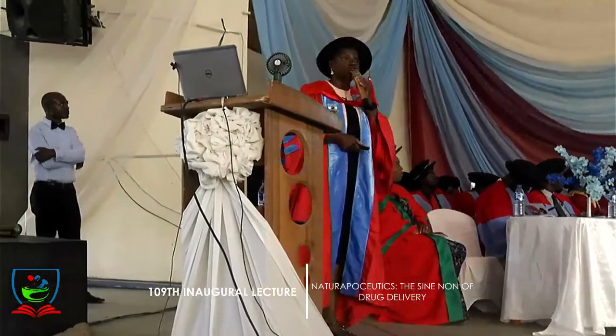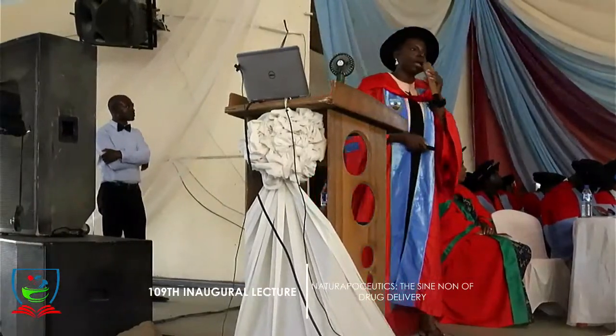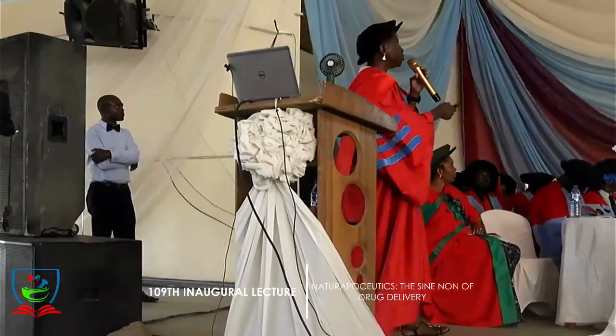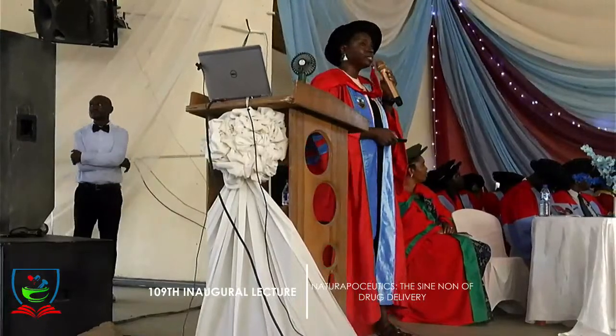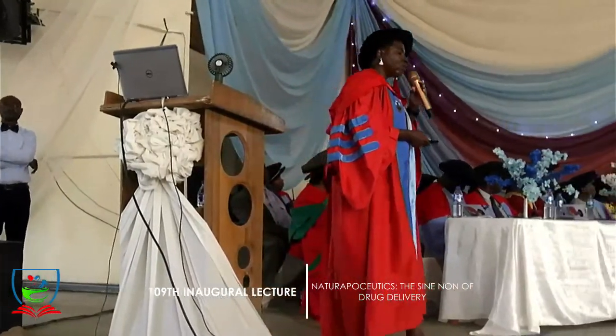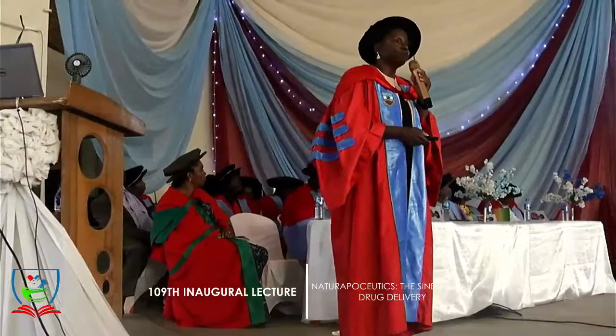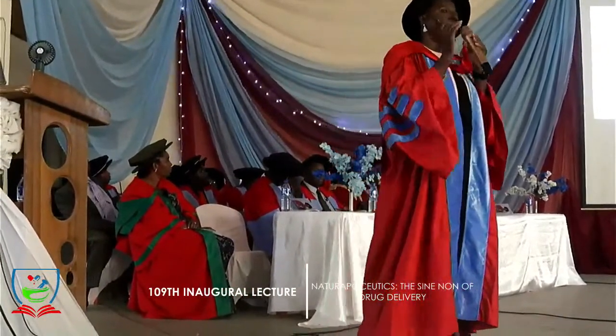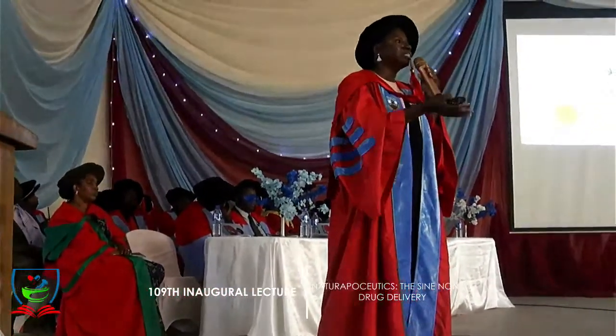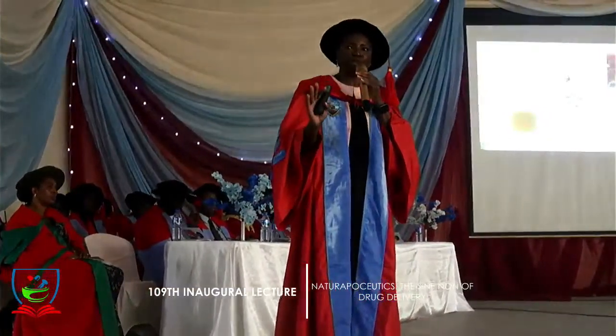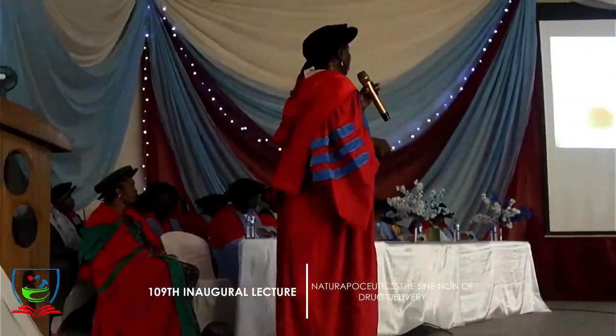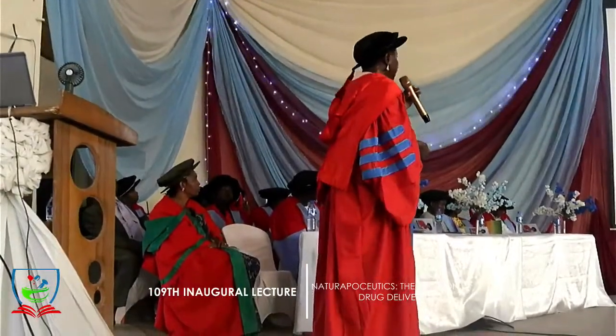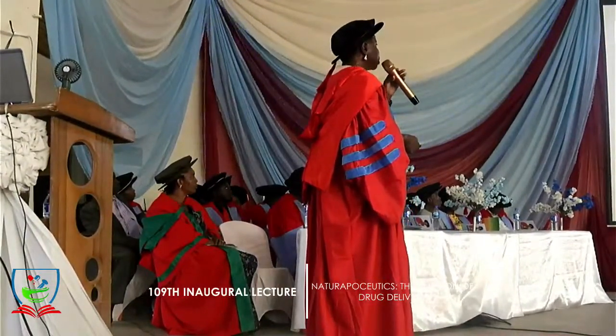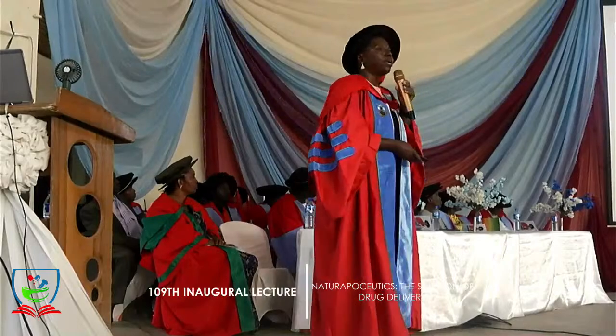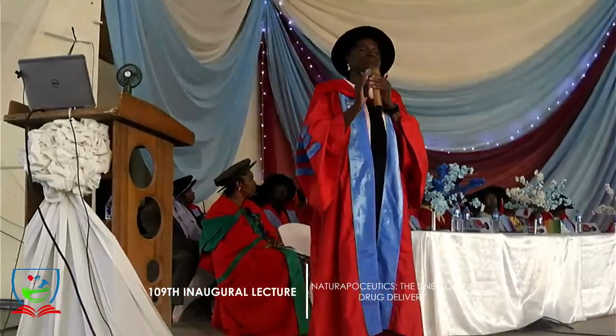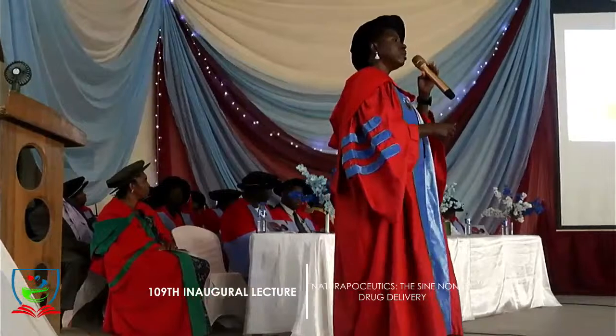Next stop is Bombax gum. We also extracted the mucilage from the red calyces and used this as a binder in tablets. We were using it for immediate drug release formulation, a situation where once you take the tablet, it breaks into pieces and the drug is available for absorption and action. However, when we did that, we found out that it didn't disintegrate and it released only 50% of the drug in 1 hour. That tells us that Bombax gum should not be used for immediate drug release.